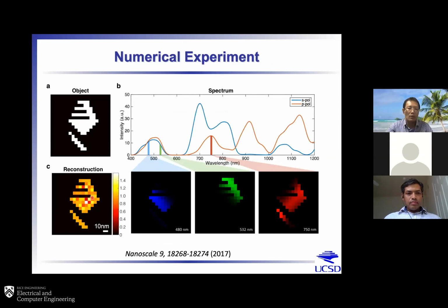Okay, of course, you can see here some noise, but this pixel size is about 6 nanometers. So by using practical material properties and scattering coefficients, and all the optical conditions, if it works very well, we probably can give a resolution at the sub-nanometer level. But apparently, there are so many things that need to be done to go through the whole experiment.